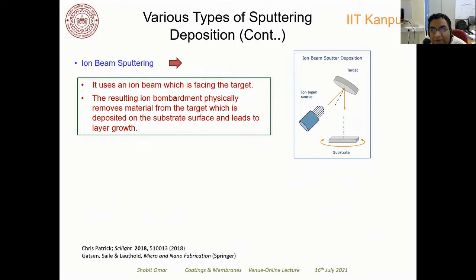Now, we also use the ion beam sputtering technique. So in the previous case, we used plasma, right? This sputtering technique uses an ion beam. Collimated ion beams are directed to the target surface at a particular angle, and then you have a substrate which is rotating, and the sputtered atoms in the vapor form get deposited on the substrate. So this is how the deposition occurs. You can see that in this particular case, we are using the ion beam as a physical process to deposit a thin film on the substrate.